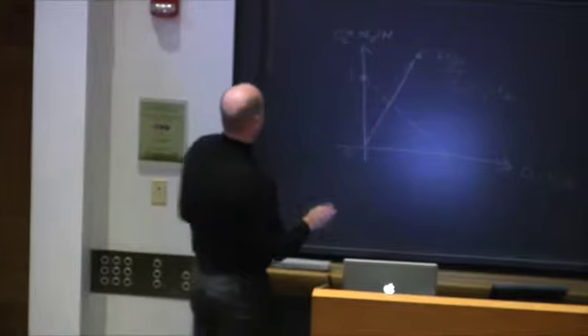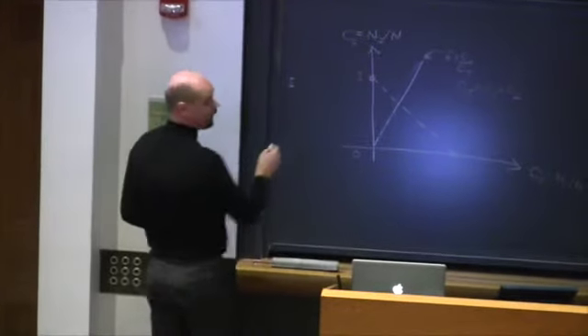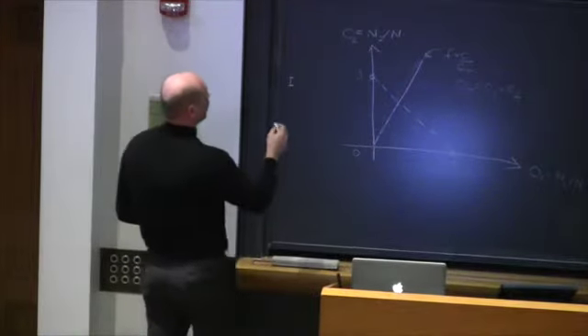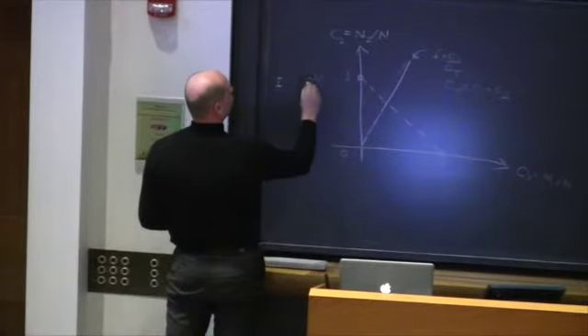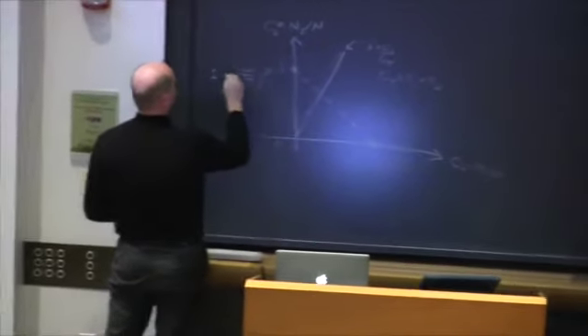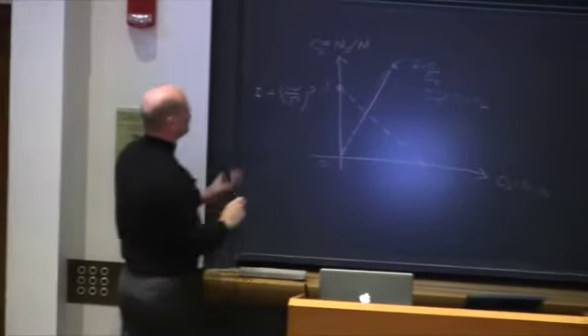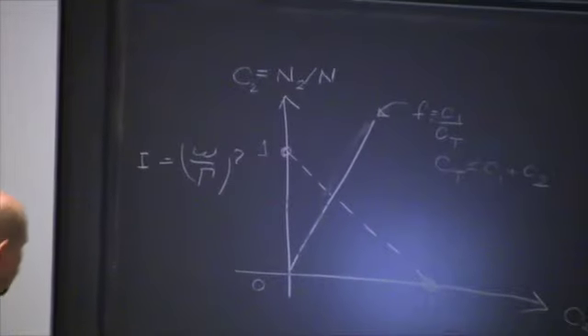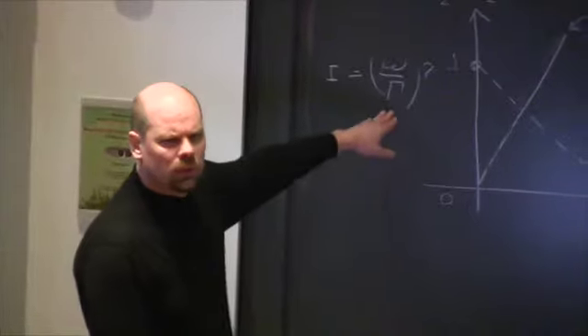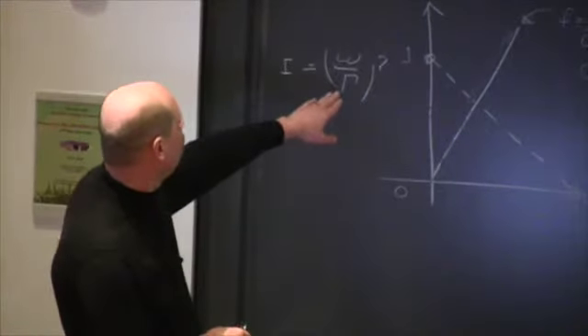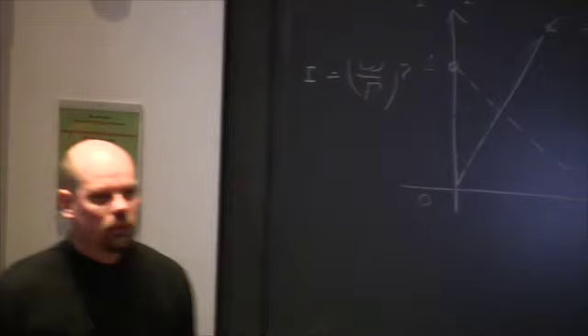Correct. So if you calculate what the intensity is for a phonon loss, it's omega over gamma to some power, squared. I think it's omega over gamma squared times the intensity of what you find for magnetic excitations or for DD excitations. So gamma is big, you say? Yeah, gamma is on the order of half an eV, 250, I think. Now phonons are smaller. So that's the same. That's correct.